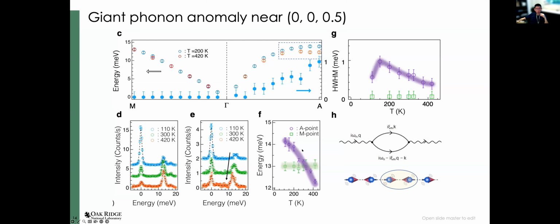So the band renormalization, this panel compares the temperature-dependent phonon band renormalization as a function of temperature. For the Γ point, you see no change. But if you go to the A point or the half L peak, you see about 14% phonon renormalization from the magnetic transition temperature to the CDW transition temperature.